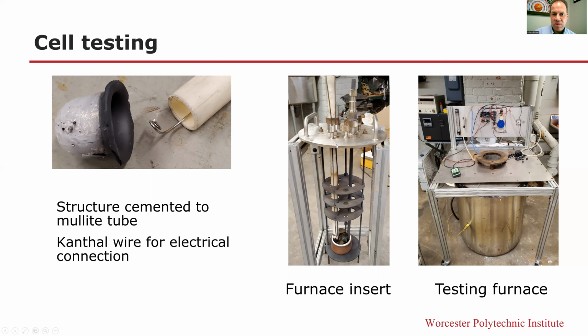So we mounted this inside of a furnace with a small crucible holding the liquid metal, and we used a graphite current collector on the anode, which, if necessary, if the carbon concentration drops in the metal, then that graphite electrode can dissolve into the liquid metal. We would use something like biochar or charcoal in the liquid metal in order to feed it typically.